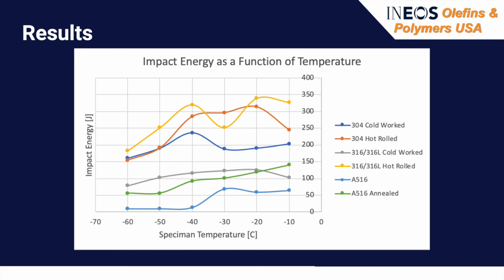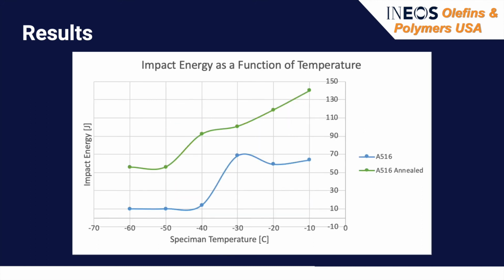Temperatures varying from -10 degrees Celsius to -60 degrees Celsius were tested. The ductile to brittle transition curves for each metal and heat treatment combination can be seen. The stainless steels 304 and 316 had higher impact energies than carbon steel. However, they are also much more expensive and not necessary for the applications INEOS was looking for. As a result, the team decided to move forward with the A516 carbon steel annealed.